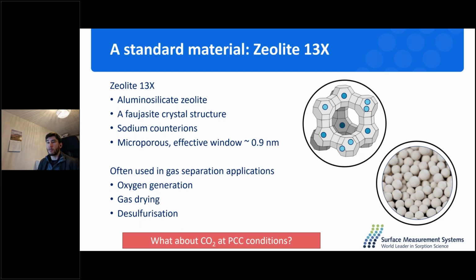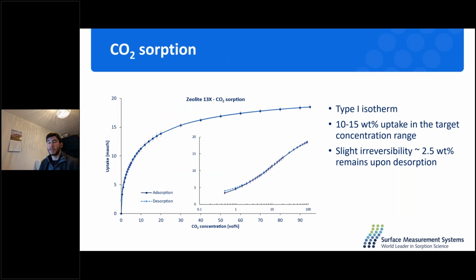So the first thing that one might do would be to measure a CO2 isotherm on the material. And this is the corresponding CO2 isotherm. You can see it's a type 1 isotherm, and it has a reasonably high uptake of CO2. At 100% CO2, it's about 15% by mass. And if we look at the range for post-combustion capture, let's say around 10 to 20%, it also has 10 to 15 weight% in this concentration range.